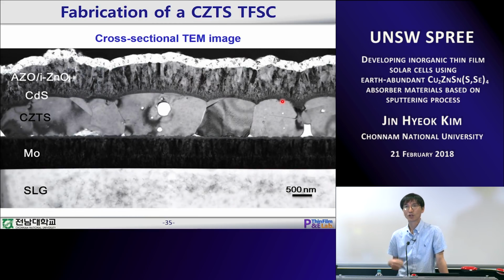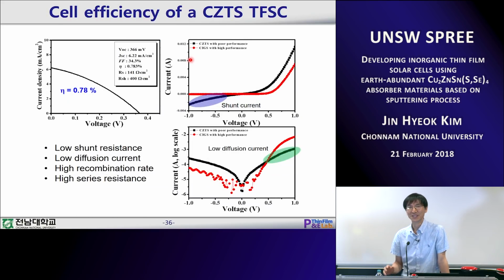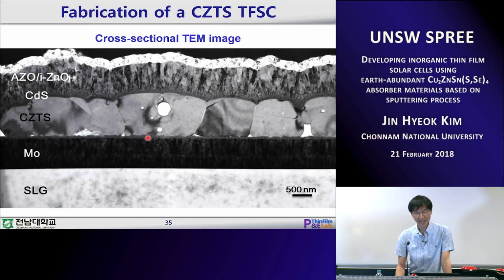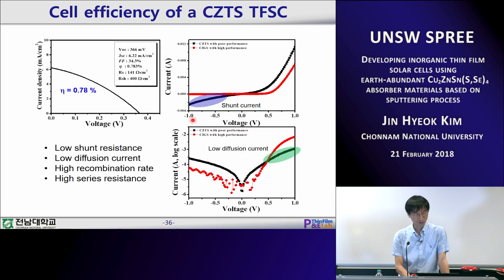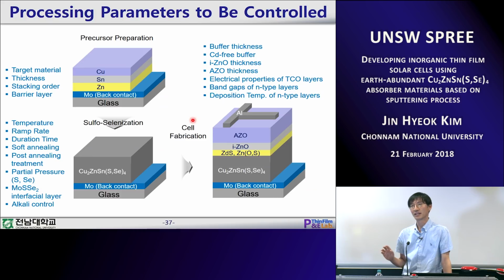And this is a cross-sectional image of the cell structure. You can clearly see the glass substrate, molybdenum back contact, absorber layer, very thin buffer layer, window layer, and aluminum top electrode. So it looks very nice. But if we measure the cell efficiency, it gives 0.78%. Very poor. That means even though we have a very nice absorber morphology, that doesn't guarantee a very nice cell efficiency. So to improve the cell efficiency, there are many technical issues.